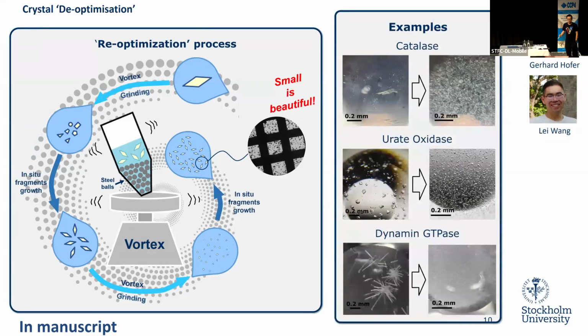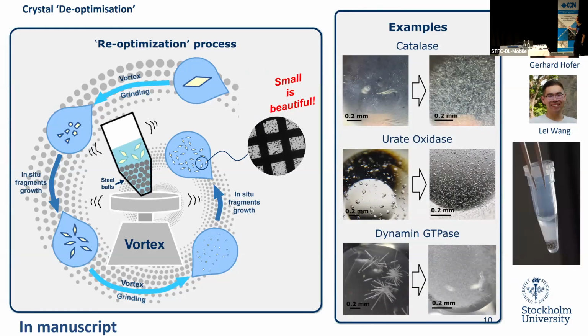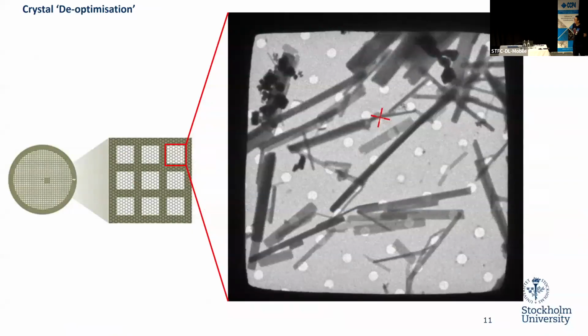Gary has tried this with multiple examples, most of them non-standard, non-model proteins. And usually what we get is a milky-looking suspension. If we can see crystals under the optical microscope, they're already too large. So we really want to see this kind of consistency at the end of this process. And what we can then have is, on a typical TEM grid, which has about 200 to 300 mesh, from each mesh, tens of crystals in principle that can be used for single crystal data collection using the rotation method.